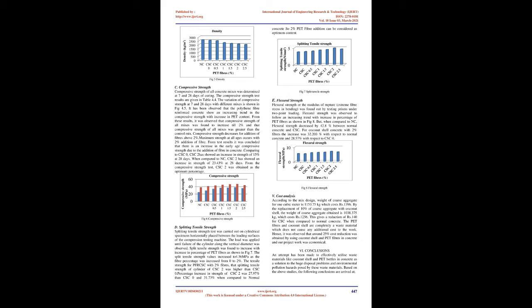4. Increase in compaction factor between NC and CSC was noted to be 19%. For PFRCSC with 2% fibers, the increase was 12% and 6.4% with respect to NC and CSC respectively. Results and discussions. A. Workability.